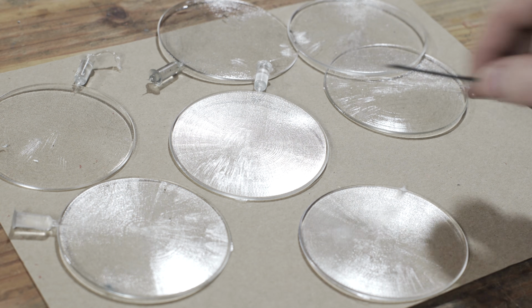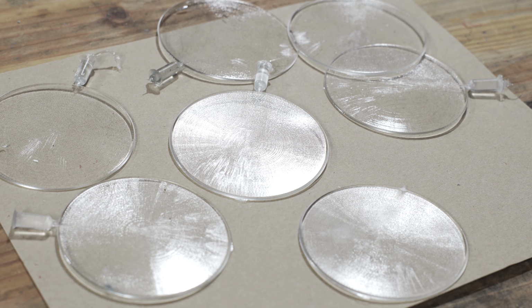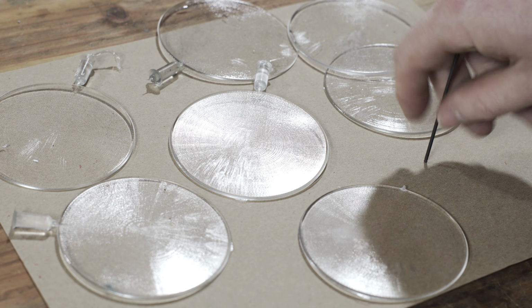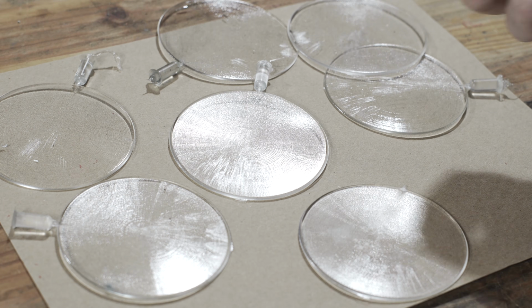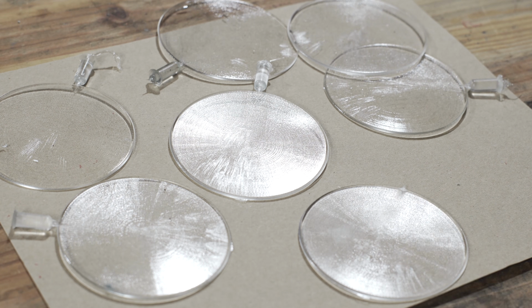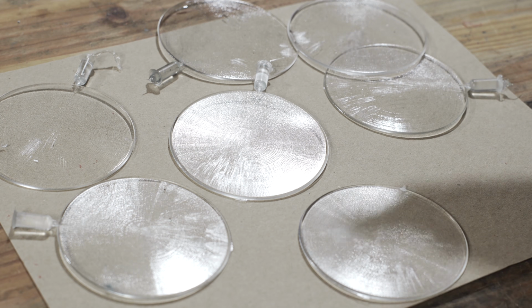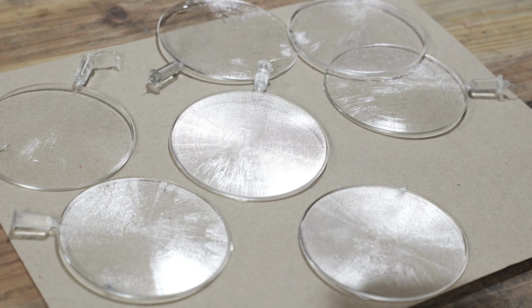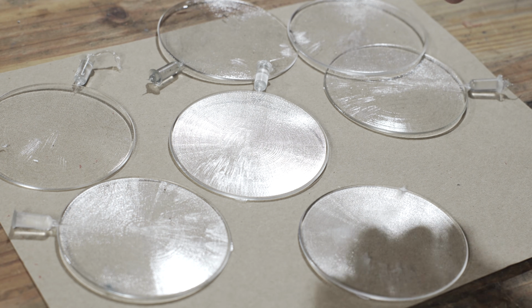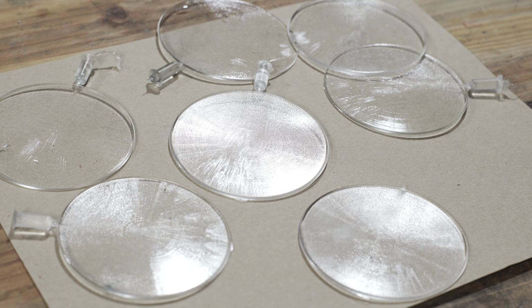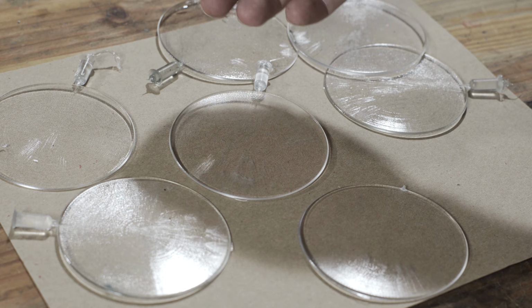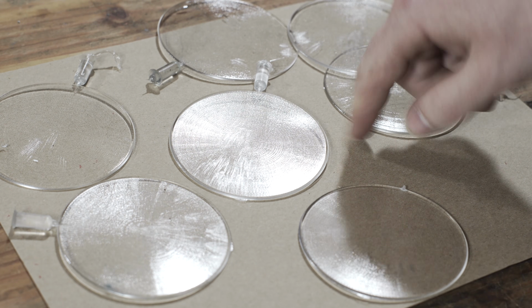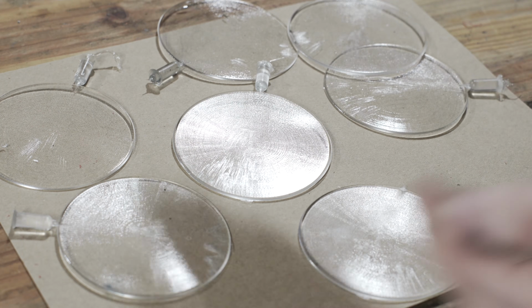But from what I gather, these are caused by one of a few sources. It's potentially possible for the injection pressure or temperature to be causing it due to too much shearing action in the polymer or decomposition products inside the resin as it's being injected. But in almost all likelihood for my case, this is just caused by moisture in the acrylic. Acrylic is hygroscopic, which means it absorbs moisture, something like 1 or 2% just sitting at room temperature. And when you're injecting this, I believe I was injecting at 420 degrees Fahrenheit, which is like 150, 180 Celsius, essentially the water that's been absorbed into and onto the surface of the resin pellets boils, and it causes this streaking as it smears out through the mold.